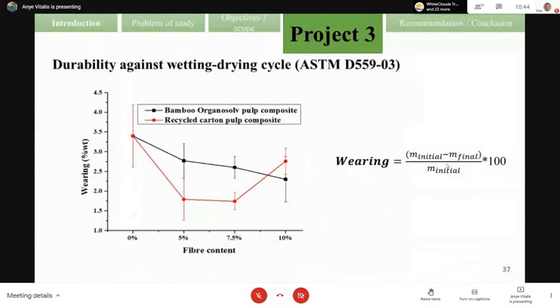So we study also the durability against wetting and dry, by using ASTM standard D559. We realize that by using 12 cycles of wetting and dry treatment and applying washing of the surface of the material, the fiber was significantly reduced.